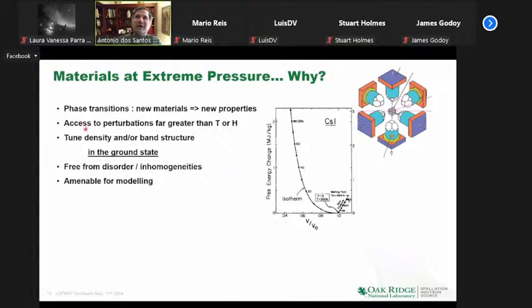An interesting one is that you can access perturbations, as you can see here, far greater than temperature or magnetic field. As you can see, the free energy change with accessible pressure is much higher than what you can do by the time you vaporize your material. The other thing is that you can do all these perturbations with pressure at or near the ground state. That is a real advantage for people thinking in terms of more fundamental physics, trying to tune Hamiltonians, where you can really change the density, see what the implications are, and then go and measure.